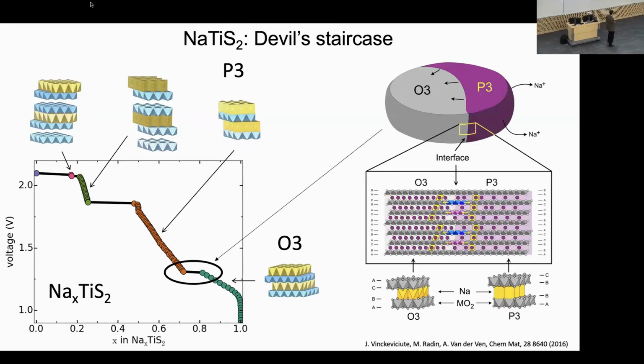This is very interesting, and it's very important for getting battery materials to work. These glide transitions are very important in these sodium intercalation compounds. They occur all over the place. And this is very similar: in O3, the oxygen sublattice is an FCC sublattice. For those of you who are materials scientists, you all know about FCC. If you want to go from an FCC stacking sequence to, let's say, an HCP stacking sequence, one way to do that is by passing partial dislocations through your crystal. To undergo a stacking sequence change, you have to pass dislocations through. So this is what's also happening here. When you go from this stacking sequence to this prismatic stacking sequence, you have to have partial dislocations that migrate through this crystal structure to realize it.